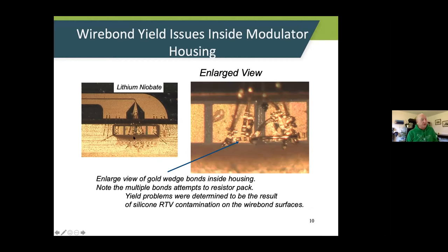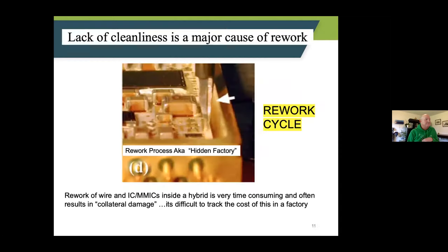Here's another example of that. Now this isn't resin bleed, but silicones, by the way, are also very dangerous to have around a wire bonder. This is an old lithium niobate modulator where, just looking at the bonding, nothing was sticking. So they just kept pounding away at it. If your wire doesn't stick, or you overbond it and it cracks, you've got to rework the wire. If you beat up the IC enough, now you've got to rework the IC or the MMIC.